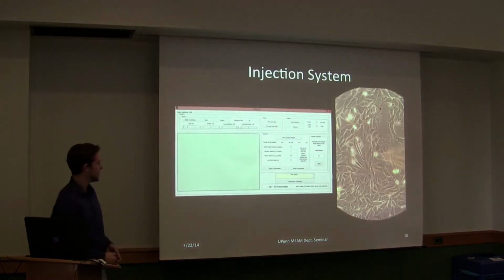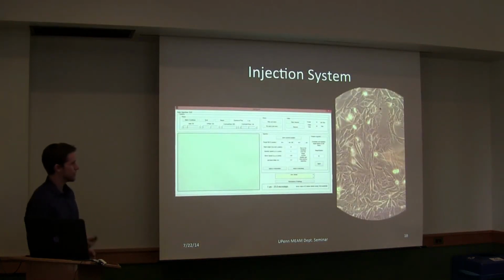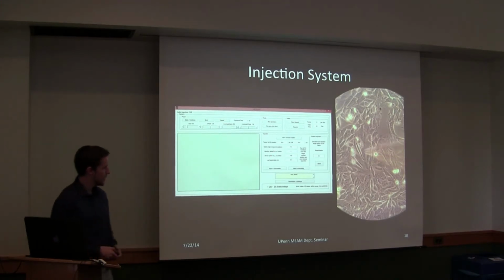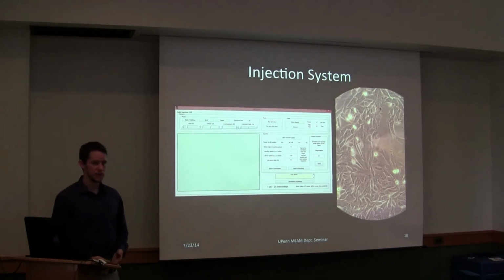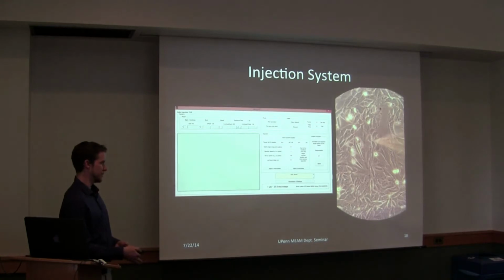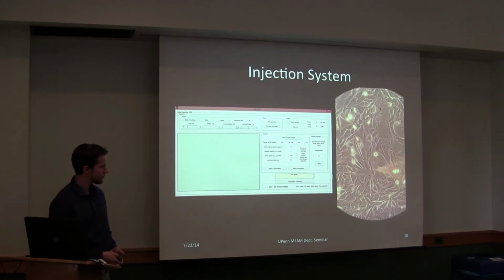So this is what the system looks like. We have this panel here for the live camera feed, so you can take videos and get your camera feed set up, along with various injection parameters. And when you have your injection parameters, such as the speed at which you're penetrating the cells and the angle that you want to penetrate the cells at, you can then go into the injection mode. And here you can see the pipette traveling around to the different injection locations, lowering into the cells, and then injecting. So it's actually taken through the eyepiece of our microscope.